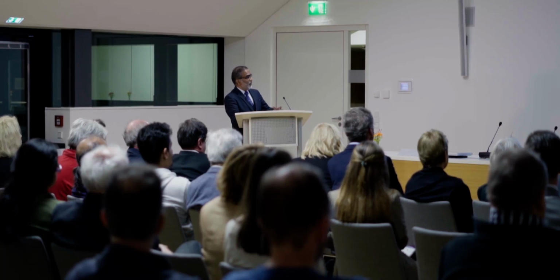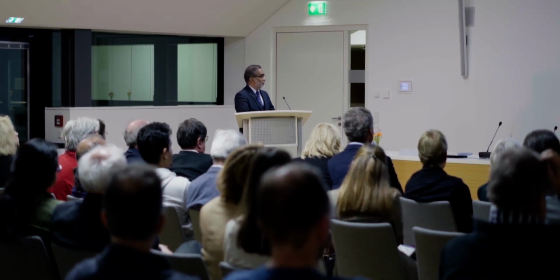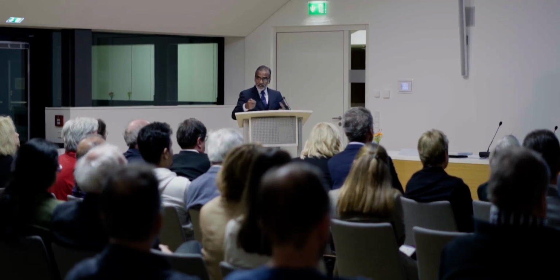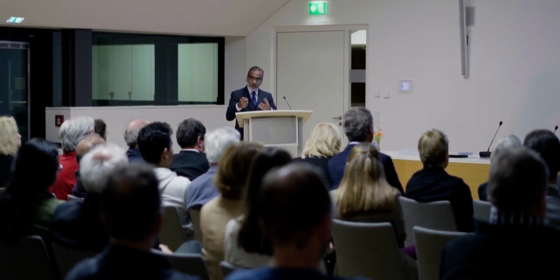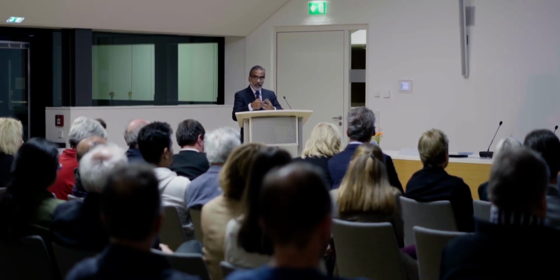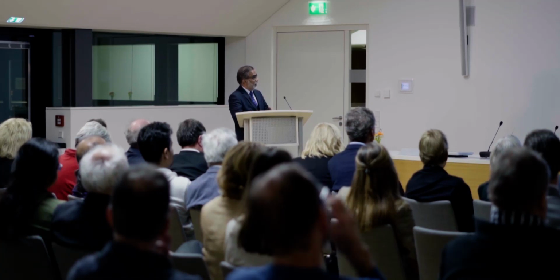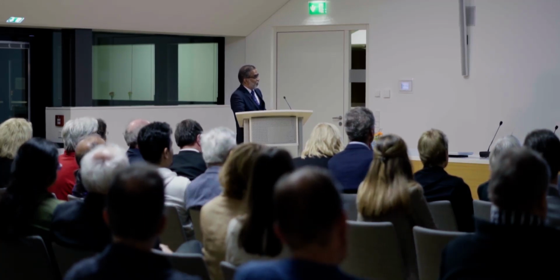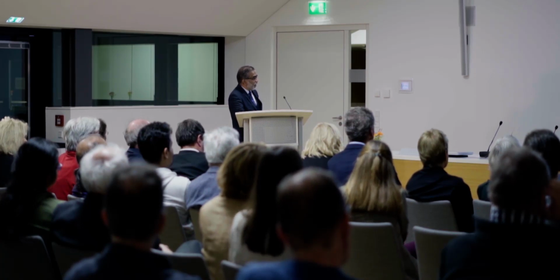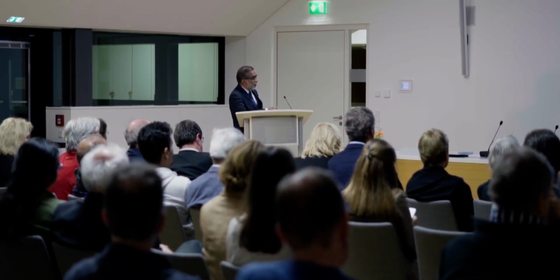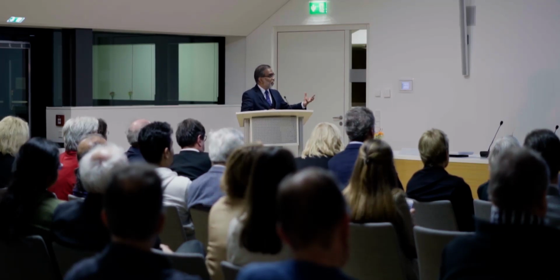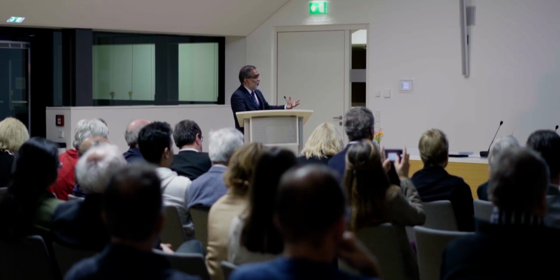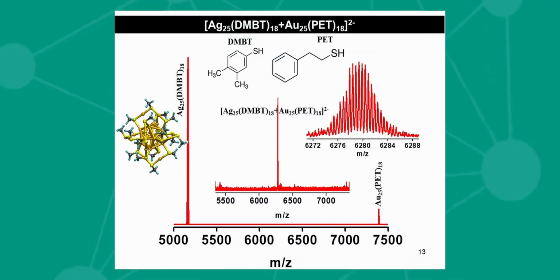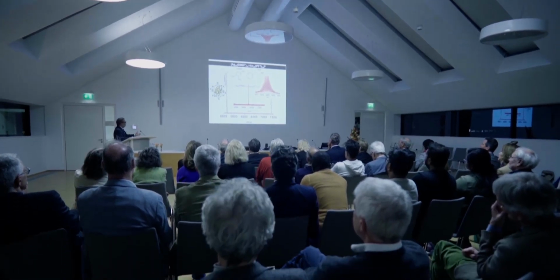Okay, so how do they react? Well, if a cluster and another cluster were to react just like molecules, they should come together and form a transition state of some kind. And can I have a transition state? So in the initial stage of this reaction, if I expand this region, I get a peak here, which is nothing but two clusters coming together and forming a dimer, a heterodimer, so to say. This is one charge state, 1 minus, this is 1 minus. They come together and form a 2 minus charge species. And we study this and all that.